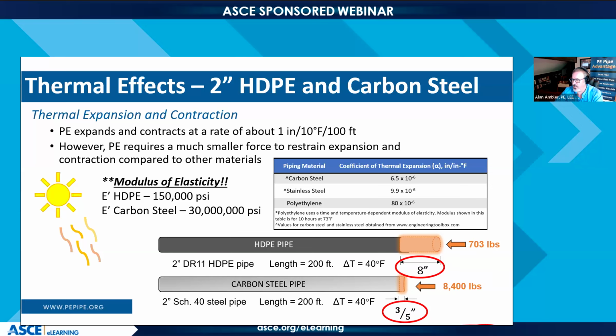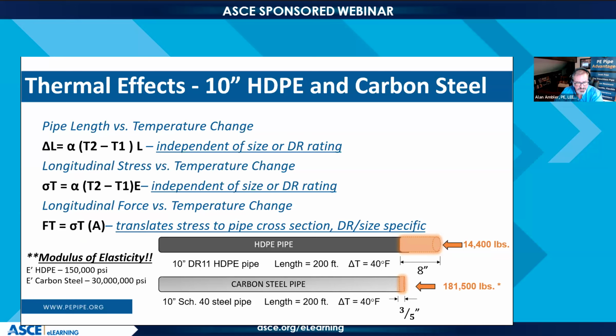However, it would take significantly less force, in this case 703 pounds versus 8,400 pounds, to restrain that pipe from moving. So this calculation is put through to get us a force over the actual wall thickness of that pipe. The expansion itself isn't a function of wall thickness or even the diameter, as we'll see from the very next example, that the 10-inch DR11 at the same length will still expand the same amount, but generate significantly larger forces because we're transmitting that stress across the cross-sectional area of the pipe itself. So those are certainly unique properties to HDPE, and we'll talk a little bit more about some of this later, unless somebody wants to add something in particular.